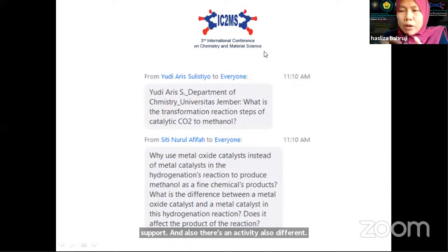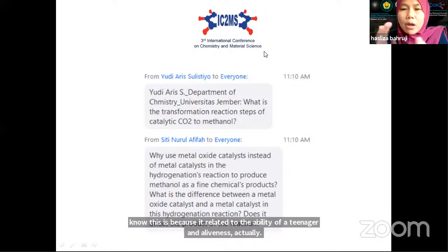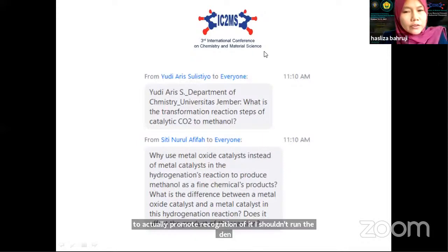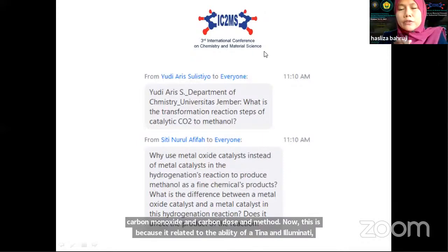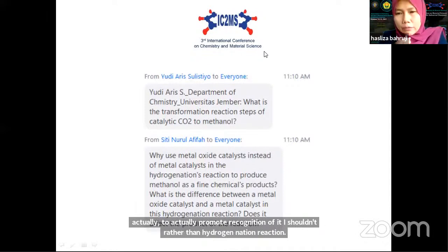I showed you at the very beginning of my talk, when we have titanium and alumina, we started to produce methane instead of carbon monoxide, carbon dioxide and methanol. This is because of the ability of titanium and alumina to promote the methanation reaction rather than the hydrogenation reaction. Yes, metal oxide support will have a significant effect on the activity of the metal catalyst that we use.